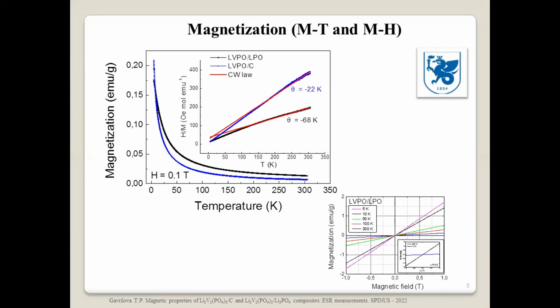Then we started from the magnetization measurements, an integral magnetic characteristic, and here you can see that the temperature dependences of magnetization for these compounds do not coincide with each other. It's normal because the chemical composition is different for these compounds. But what is interesting is that if we try to fit high temperature data using the Curie-Weiss law, we will see that the Weiss temperature is much higher in absolute value, I mean, it's much higher for the compound with lithium phosphate. We suggest that it means the presence of short-range magnetic correlations in this compound.